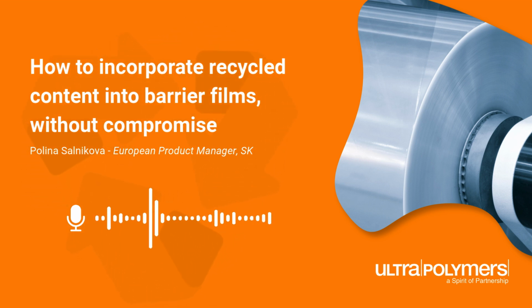Why PE/EVOH? Polarity matters when adding recycled content. As described earlier, films incorporate multiple layers of slightly different materials that bring different properties to produce a high-performance system. Continuing with the example of PE and EVOH, this combination of materials is great for the recyclability of the product, as PE and EVOH come from the same polymer family, polyethylene. However, EVOH is polar, whereas PE is not. This is problematic when making films because like attracts like.